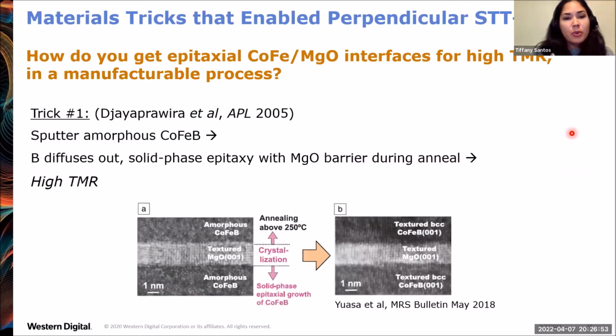Okay, so at this point, I want to tell you a couple materials tricks that have enabled perpendicular spin transfer torque MRAM. My role in the team is to deposit by sputtering the film stack of magnetic tunnel junctions. And so these are tricks that we're really using day in and day out, and that have enabled this technology. So one is, how do you get an epitaxial cobalt iron MgO interface that's needed for high TMR? How do you get that high quality interface in a manufacturable process? So this trick here was found and published in Applied Physics Letters in 2005.